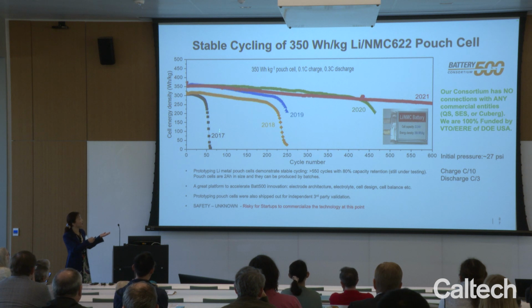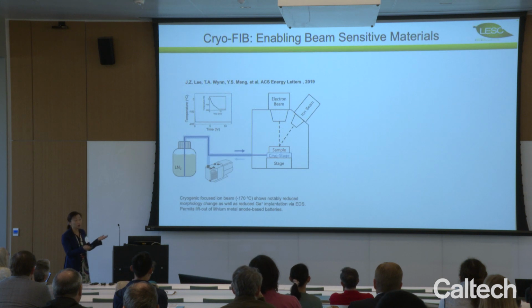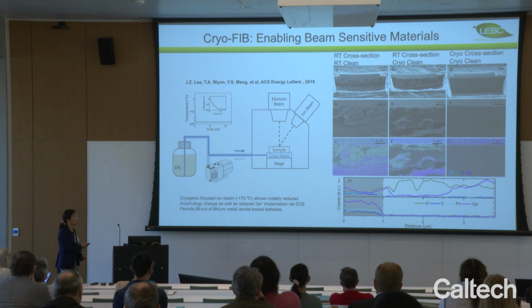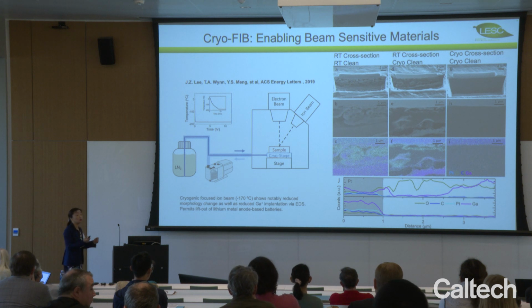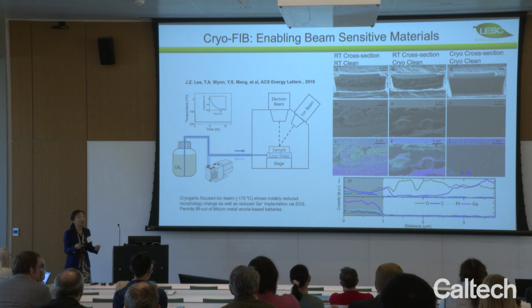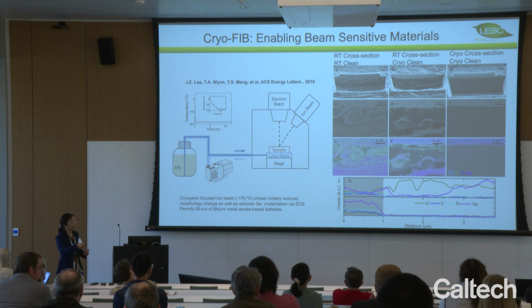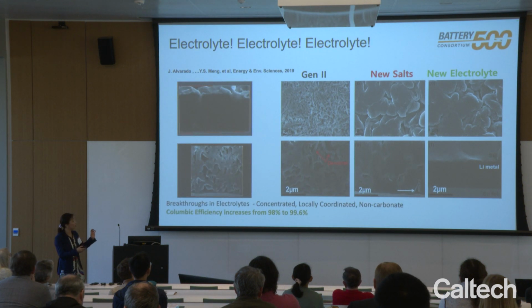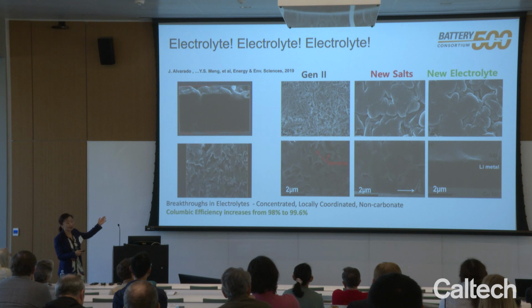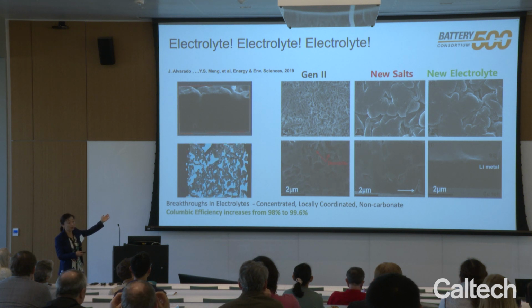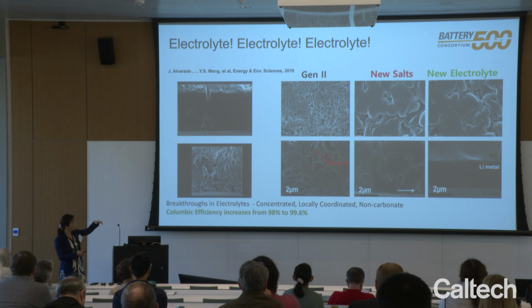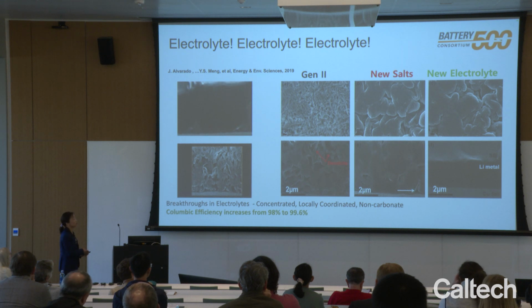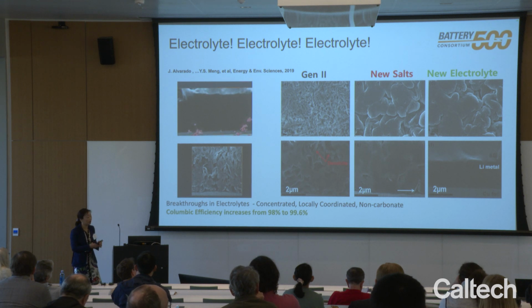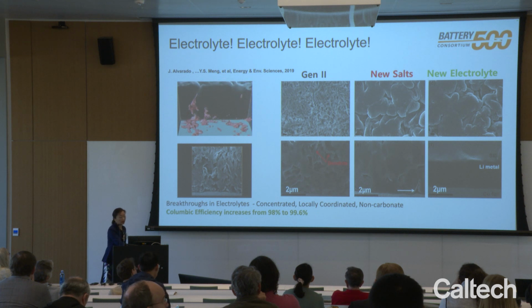When we first started, every cell failed after 50 cycles. I'll show you why lithium metal is so difficult to observe, because the tools we have are not good: the gallium FIB beam will interact with lithium. So we have to bring it to cryo temperature. But just this simple tool advancement explains why the early lithium metal cells could not work. You look at this electrochemically deposited lithium: more than 50% of that is pores. And then when we change to the new electrolyte developed by the national laboratory, Pacific Northwest, you can finally get lithium that is 100% dense.